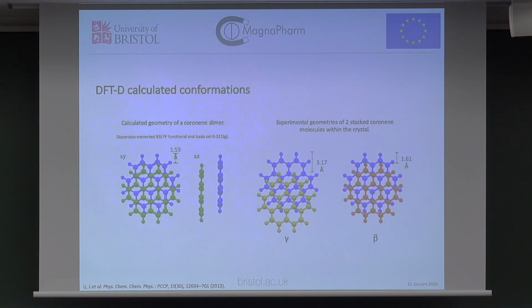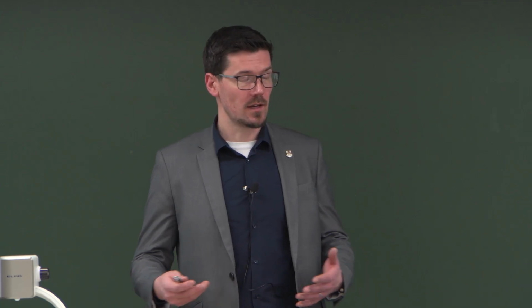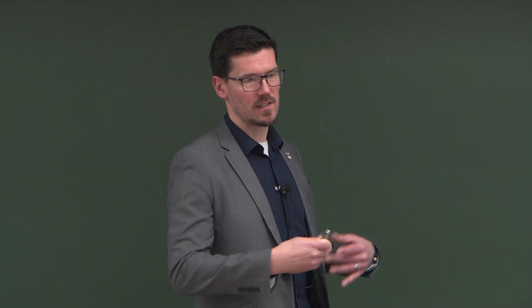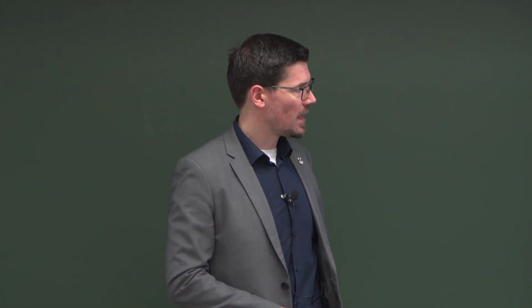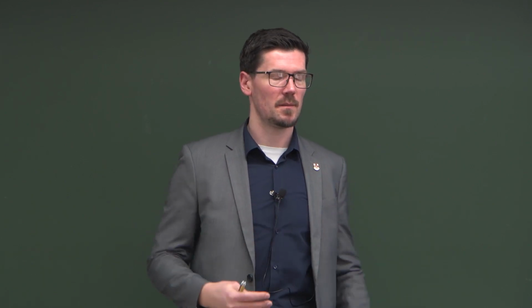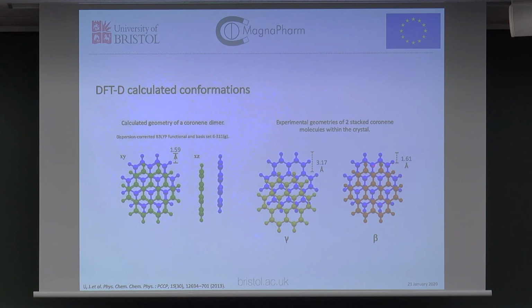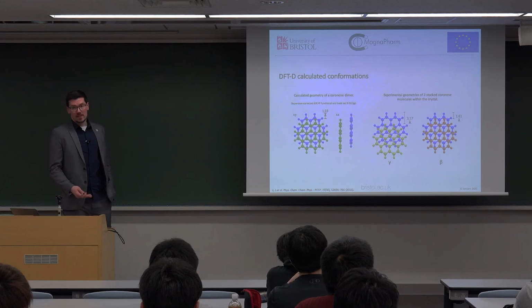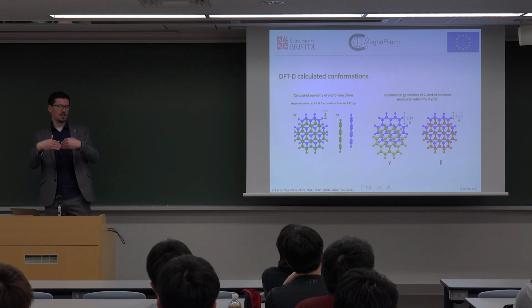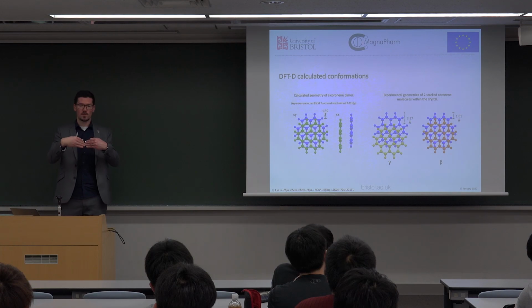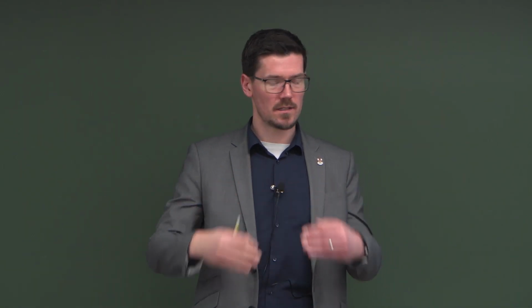In gamma coronene, the one that everyone knew about before, what we had was this 3.17 angstrom offset, and it was commented on a number of times, why don't we see the 1.59 offset in coronene crystals when this interaction is so favored energetically? The edge face interactions must really be stabilizing the crystal. But in beta coronene, we actually have a 1.61 angstrom offset, which mirrors the calculations done over the last few decades of these 2 things interacting, which implies that the edge face interactions of these crystals are drastically minimized, which would also justify why that angle is so much less.